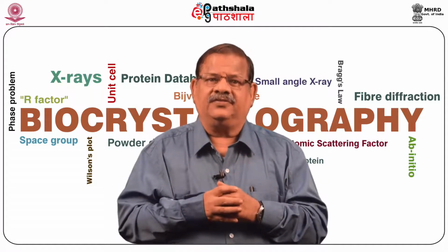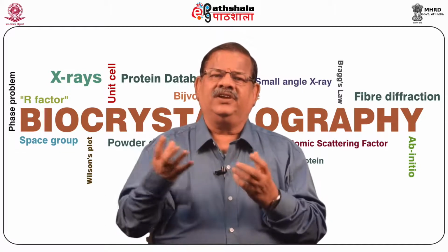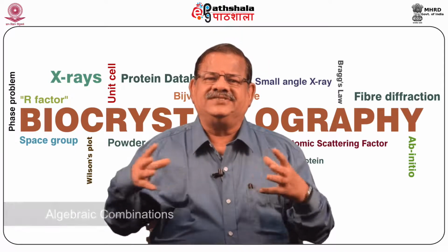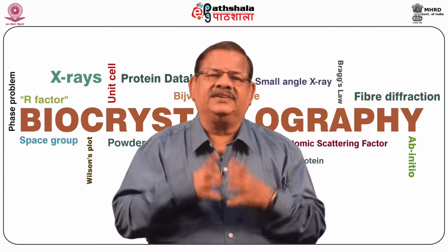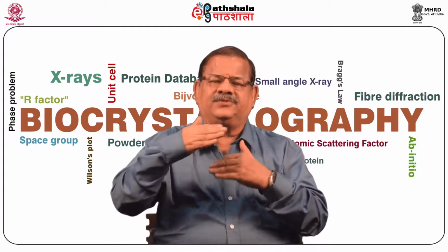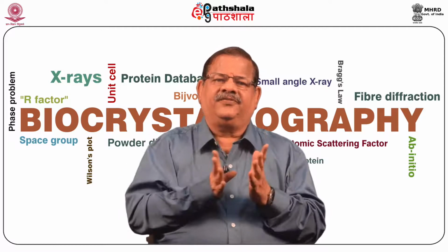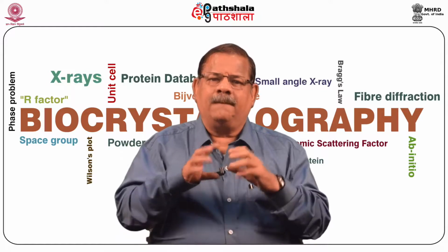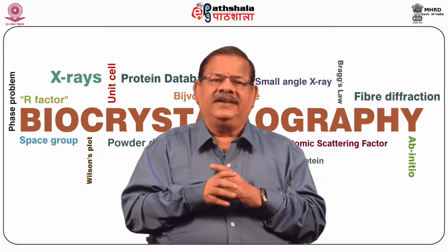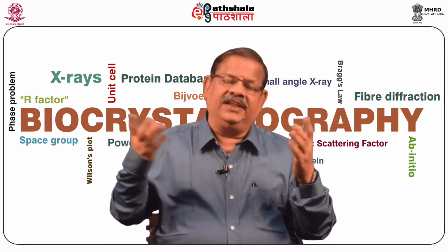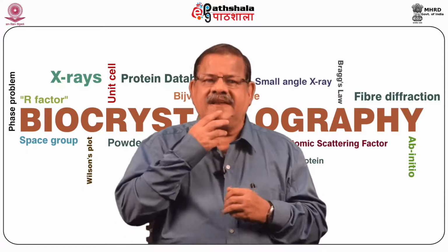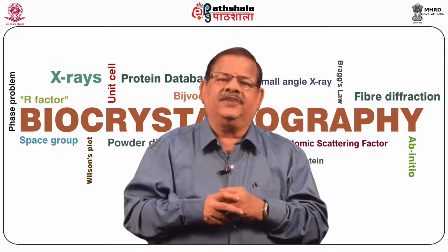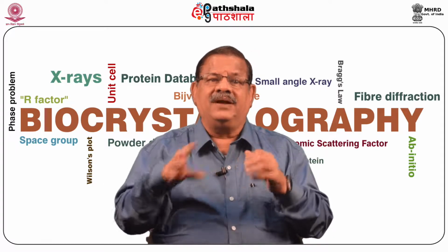Now let us consider the effects of multiplicity and measured arc length. In a powder photograph, space group symmetry often introduces the possibility of planes with different algebraic combinations of the Miller indices HKL having the same spacing d and therefore diffracting in the same halo. This factor, little p, is known as the multiplicity factor, and it takes different values for the various crystal classes. Hence, the intensity of diffraction into a given halo is increased by this factor as a multiplier in the above equation.